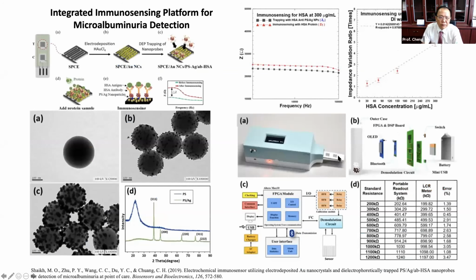So in the first step, we try to develop the paper-based sensor. You can see this is the paper-based sensor, and we use a screen printing electrode on the paper-based sensor, and we do electrodeposition with gold nanocrystal on the carbon electrode surface. Then we use the DEP trapping. Like the previous bladder cancer chip, after we modify the nanoparticle, we can use the DEP force to immobilize it onto the electrode.